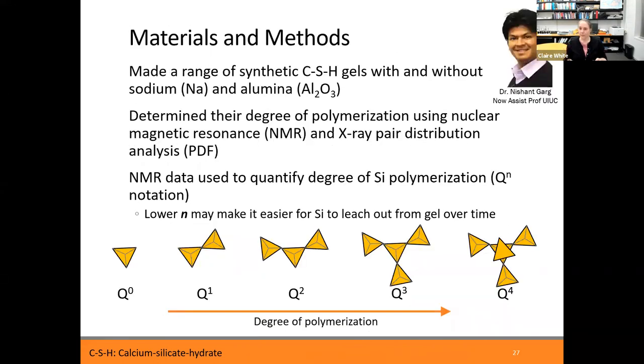So these gels were made with and without sodium and alumina. And what we did, once we synthesized them, was use nuclear magnetic resonance to look at the silicate connectivity in the gels. We also used a technique known as X-ray pair distribution function analysis to look at the local structure of the gels. Firstly, NMR was used to quantify what's known as the degree of silicate polymerization in the gel, where down here is what the silicates can do.